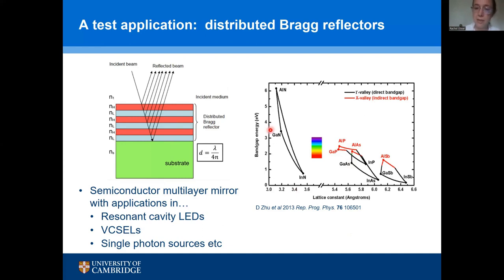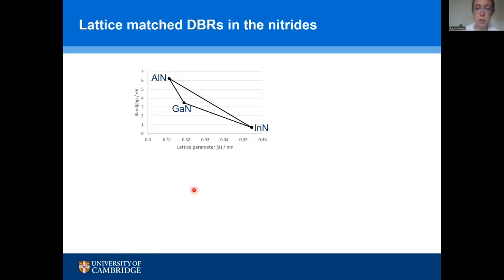The trouble we have is that gallium nitride doesn't have the same lattice constant as aluminium nitride. The spacing between atoms in those two materials is different. And indium nitride, again, is different. So that means that this kind of lattice matched pair of binaries that we have in the arsenides that lets you do nice tidy growth to get beautiful multi-layers isn't really applicable in the nitrides. I'm just going to zoom in on that part of the diagram.